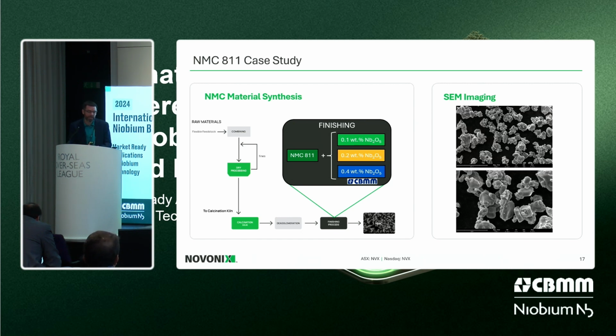So we are screening surface coatings, at least in this case study, of 0.1 weight percent, 0.2 weight percent, and 0.4 weight percent of micron-sized niobium oxide as a surface coating. And on the right-hand side of the screen, you can see the beautiful single crystal geometry that we were able to achieve following this process flow.